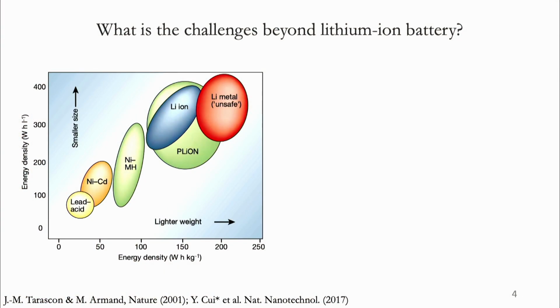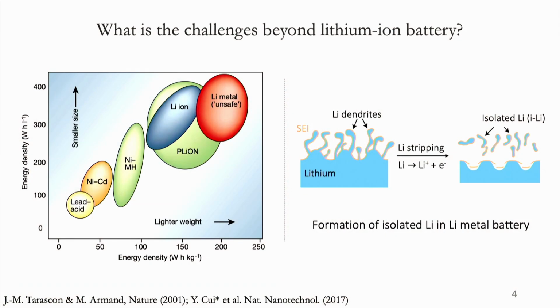So if we think about energy density in terms of a battery pack, by just replacing the anode with lithium, we can double or even triple the energy density of the whole battery pack. And as you might imagine, everything comes with a price. The electrochemical reactions of lithium metal batteries are much more complicated compared to graphite. This is actually a technology that was once commercialized in the 1990s as a primary battery. But people quickly found that this kind of battery is not safe and cannot really be recharged. This is partially because of the formation of lithium dendrites.